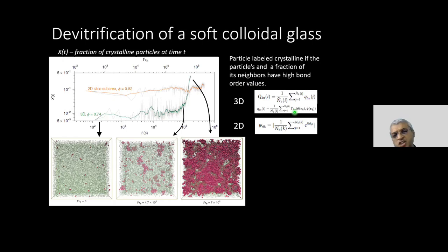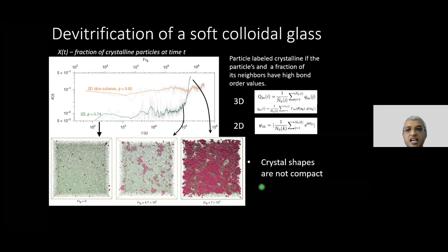The way we define a crystalline particle is basically a detail. We can go to each particle, track its local neighborhood, and calculate what sort of crystal it is, either HCP or FCC. All of that we can do by looking at bond order parameters. All the purple particles that you see here are essentially microcrystalline particles, and you see that they are increasing. The first observation, of course, is that, unlike crystallization from a liquid, these crystals are not compact. Because in the liquid, the surface tension term would have made it a very compact crystal, but that's not what we see in our glass samples.